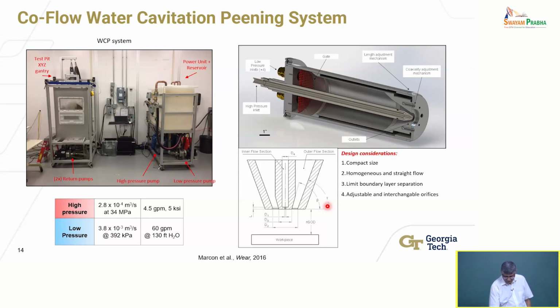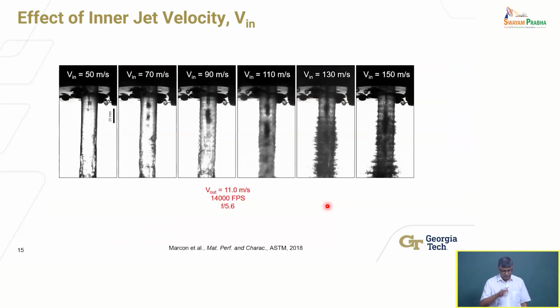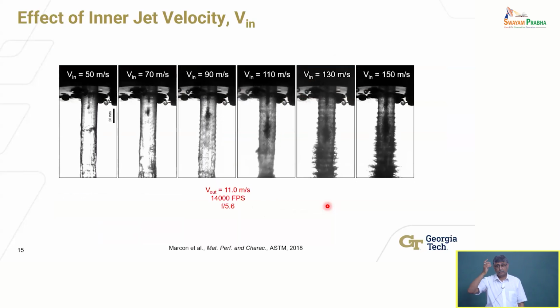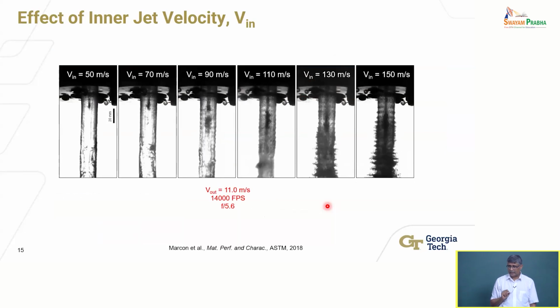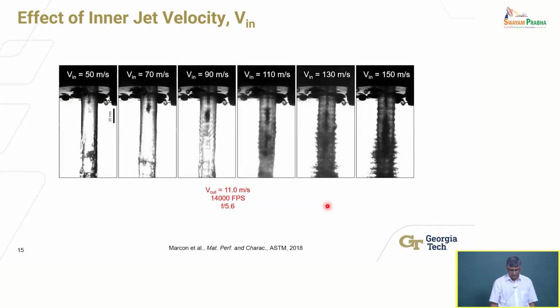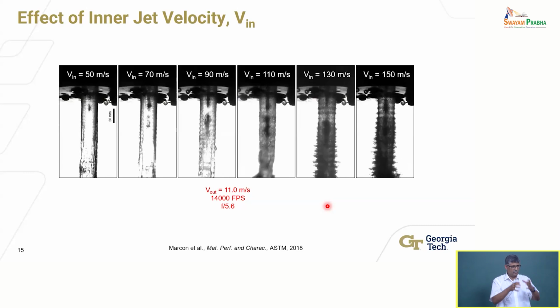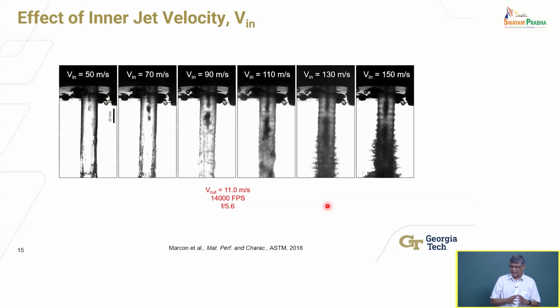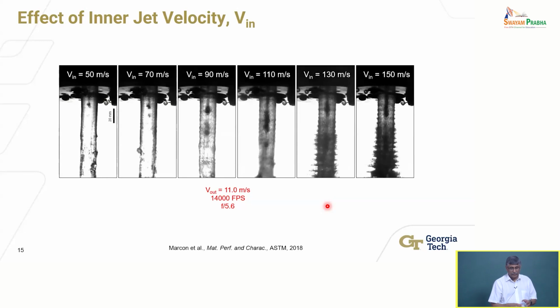But anyway, we did this experimentally first. Here's high-speed imaging, okay, of the flow coming out of that system, and showing you what happens when I change the velocity, the inner jet velocity, right? That inside pipe through which I'm injecting fluid, water. So from 50 meters per second to 150 meters per second. And what you see clearly, and the outer velocity, the surrounding low speed column of water, is at 11 meters per second in this example, right? You can see here that the cloud forms and dissipates. At low inner jet velocity, it forms and dissipates very quickly. So if I had to actually peen using that, I'd have to keep the surface very close to that exit of the nozzle. But as I increase the inner jet velocity, the size of the cloud varies and increases.